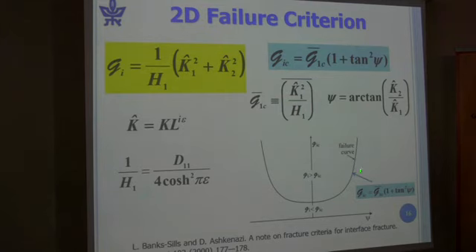Here is the failure curve, and let me explain to you what it means. Suppose I have the same interface in a structure and it's a complicated structure, and I make an assumption of the kind of delamination I have, and I say, okay, let me calculate K1 and K2. I calculate K1 and K2, and I find a value of psi, and I'm along the psi axis. You will recall that psi actually depends on L, and what L does is it translates this psi axis. So you calculate your psi for the L that you use to obtain this curve.